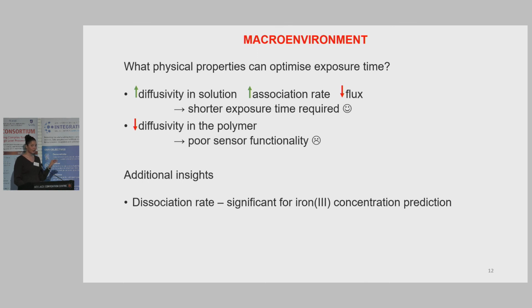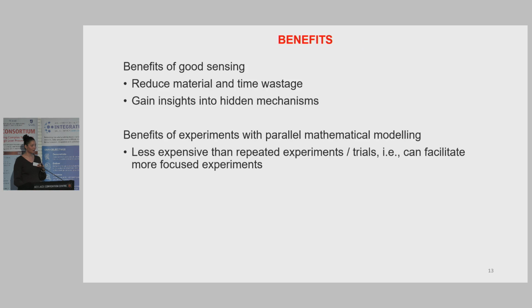If we decrease diffusivity in the polymer, we do have shorter exposure time, but this makes for poor sensor functionality because it only decreases sensor time for crystals at the surface of the polymer. What we also found out is knowing the dissociation rate helps predict iron 3 concentration in a solution.